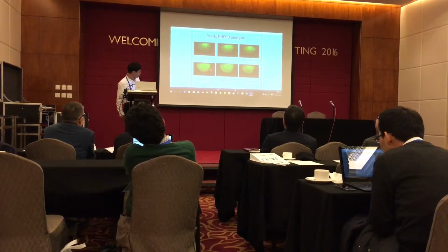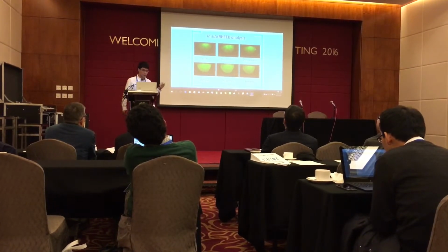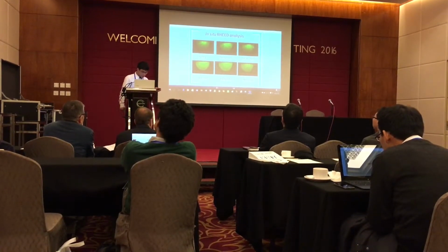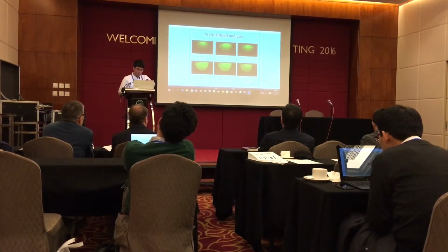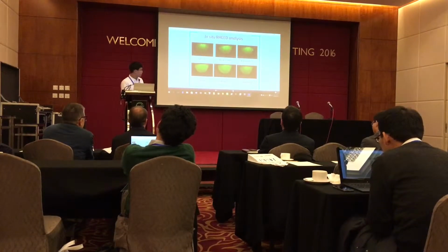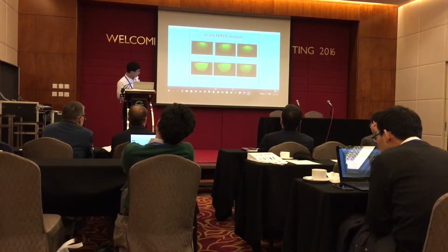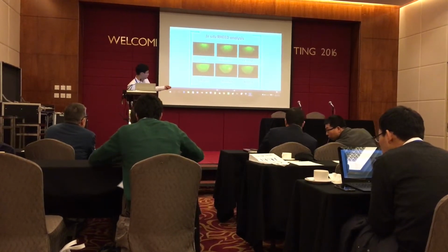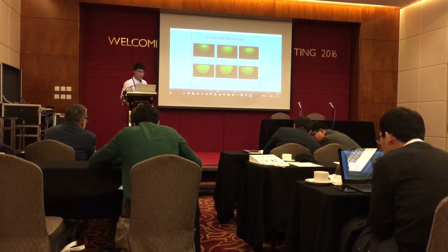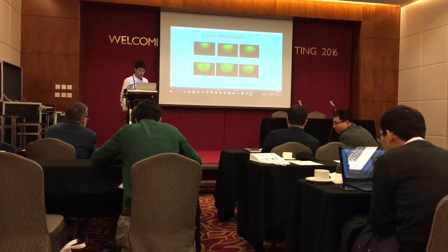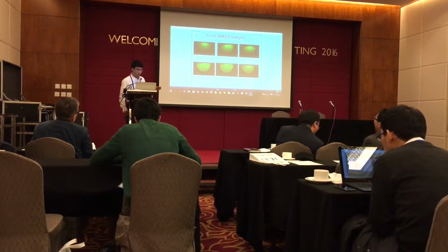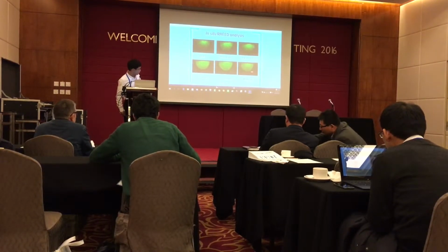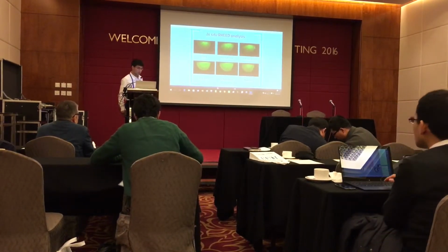Indium droplet formation: the RHEED pattern becomes spotty and foggy because the film is getting rough. In indium nitride nanodot formation, you can see the Debye ring here. It is attributed to the random orientation of the indium nitride nanodots. Following with annealing, the RHEED pattern does not change.